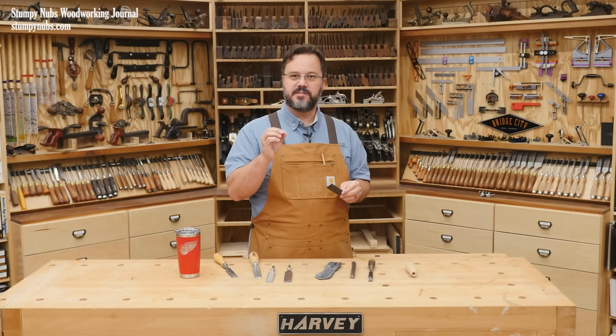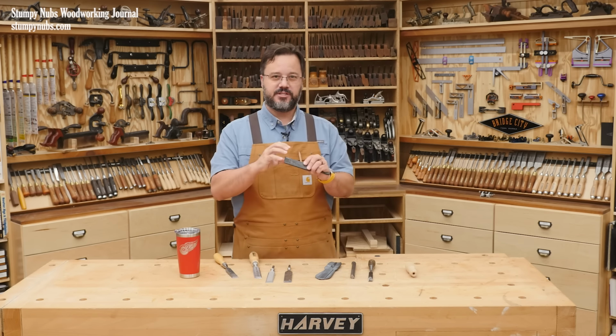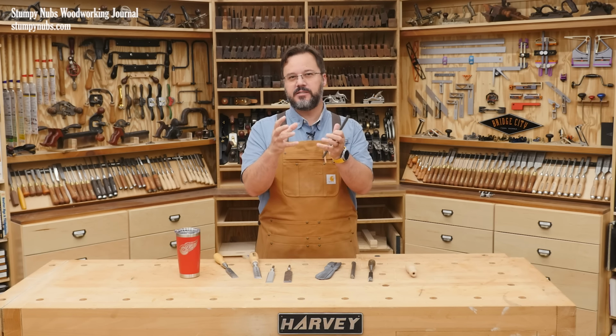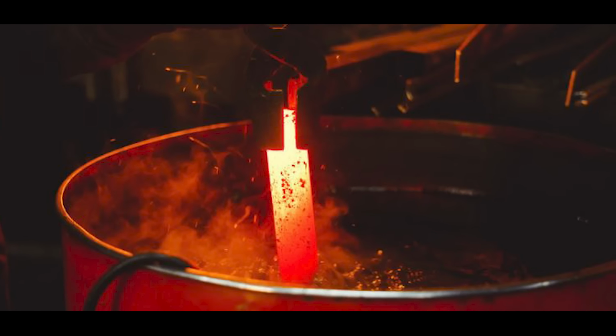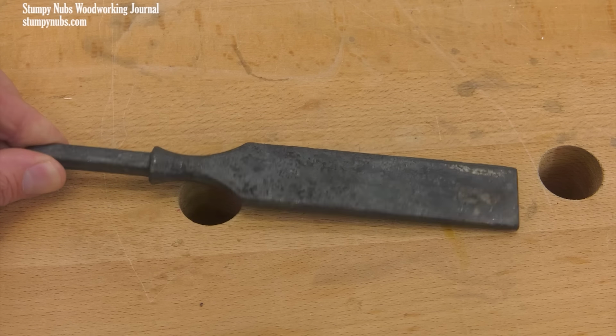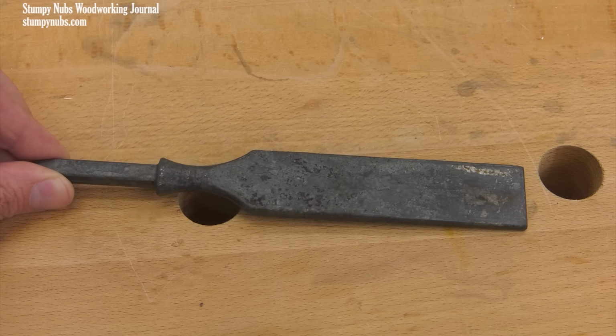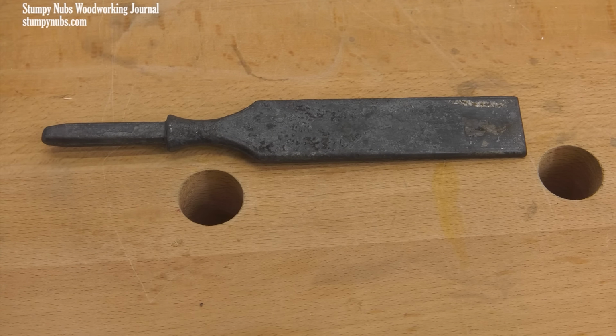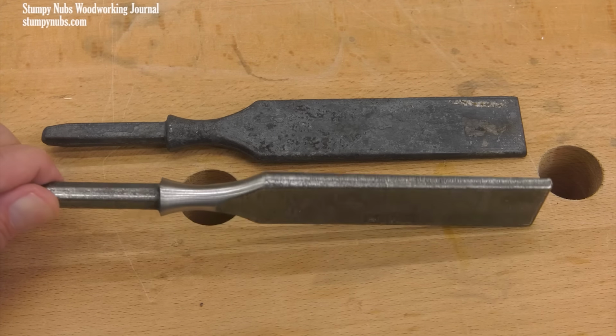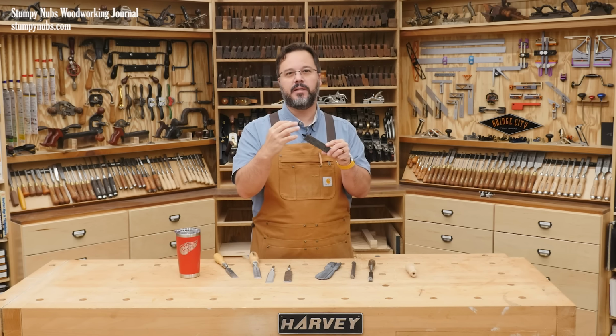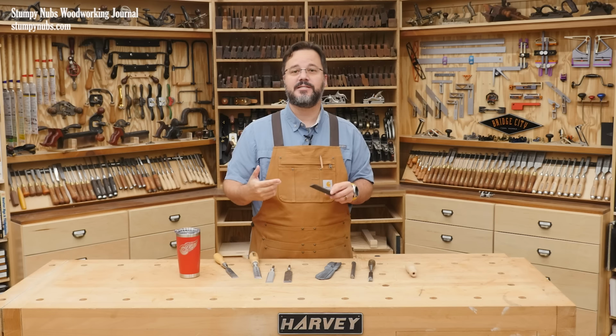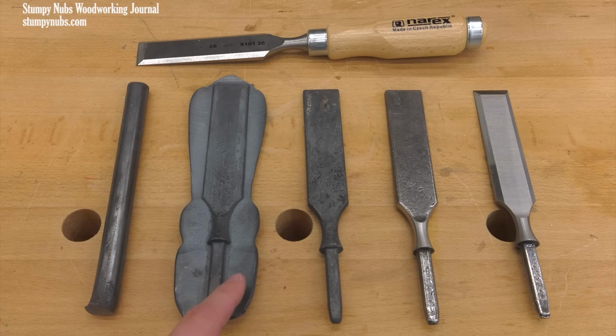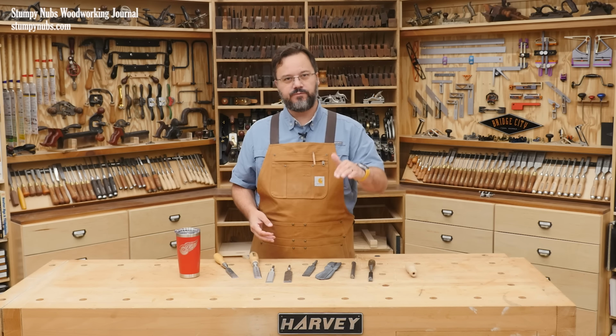Hardening involves heating the tool to a specific temperature and holding it there for a specific amount of time. This alters its structure and causes the iron atoms to separate just enough for carbon atoms to squeeze in between them, where they're locked in place by quickly cooling or quenching the tool in oil or water. The result is steel that is often more dense and harder than ever before. In fact, at this point, the tool is still a bit too hard and too brittle. So it has to undergo another process called tempering that involves reheating it, but to a lower temperature, and allowing some of those atoms to relax again a little bit. The level of heat applied during the tempering process determines exactly how hard the steel will ultimately be. The goal is a tool that's hard enough to reduce edge wear, but not so hard that it'll be brittle. The hardness is graded on what's called a Rockwell scale, which at least for woodworking tools ranges from the low 50s to the high 60s.